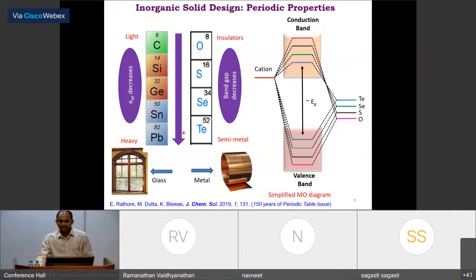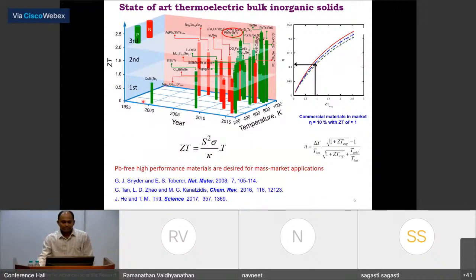At the same time, these heavy metal-based tellurides and selenides consist of heavier metals, so the lattice vibration slows down and we'll have glass-like thermal conductivity. So now we have glass and metal-like property that can be achieved down the periodic table. So that's why in our lab, we always work on germanium, tin, lead, or bismuth or antimony based sulfide, selenide, tellurides.